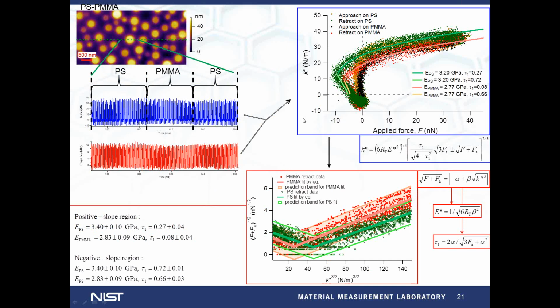For quantitative measurements, we analyzed a larger sequence of successive oscillations along a scan line, going over both polystyrene and PMMA regions. The contact model used was again the Schwarz model in the same flat punch approximation, but this time in terms of contact stiffness versus the applied force, we were able to linearize this dependence and plot the measurements both in the full contact region and in the unstable region where the tip is detaching from the surface. We fit both regions by keeping the same elastic modulus for a given material and letting the transition parameters be different from the full contact to the unstable region.